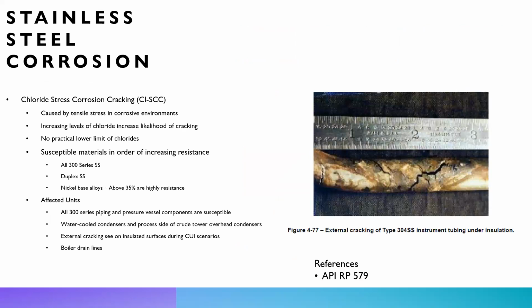And then going into what I think I see the most with stainless steel, which is chloride stress corrosion cracking. So if you guys are in the industry, you know you've seen this plenty of times where you have cracking on your stainless steel due to chloride levels in your process. Increasing the chloride levels is definitely going to increase the likelihood of cracking, but as per API RP 579, there's no practical lower limits of chlorides. The chlorides can concentrate in any area they can within the process and form this stress corrosion cracking.